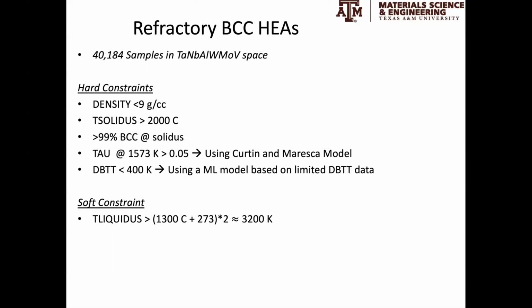And we are using some hard constraints, such as relatively low density, much higher solidus temperature - so we're looking at 2000 Celsius at least. We want alloys that are 99% or above BCC at the solidus temperature.